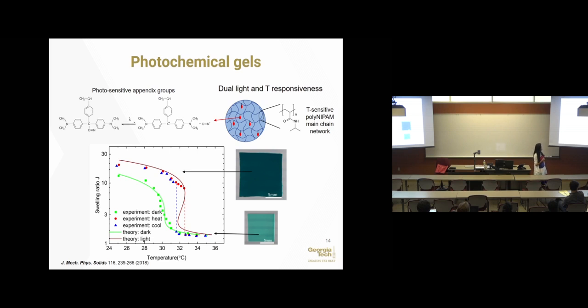And when you shine light to it, the transition temperature is shifted because you disturb the interaction property between the solvent and the molecule after you generate this dissociation. So our model can capture this transition of temperature, but meanwhile, we can capture something more, very subtle physics. So you can see in this forward process, when you increase temperature, it jumps at a relatively higher temperature and comes back at a relatively lower temperature. And our model can capture all the stationary states of a possible transition state of this phase transition behavior.